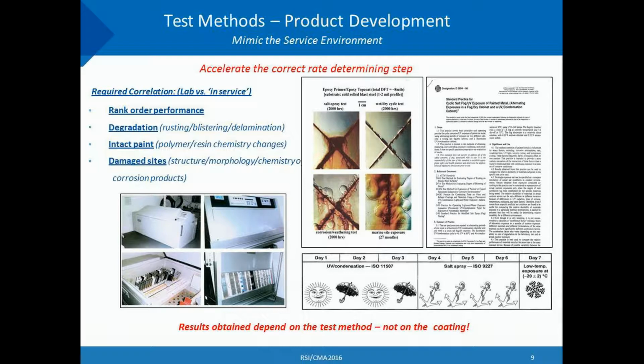In fact, you just see some corrosion in the scribe. There's really no damage further away from the scribe, and you don't see any of these solidified blisters, if you like, filled with solid corrosion products. In fact, if you tear off the paint here, it's liquid that's underneath the paint film. And these conditions are absolutely not what happens in real life at all. Just simply cycling the corrosion test does not replicate what happens either.